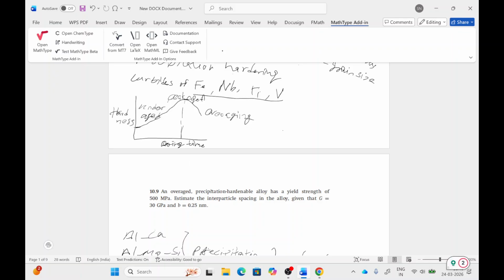In this question, we are asked: an overaged precipitation hardenable alloy has a yield strength of 500 MPa. Estimate the interparticle spacing in the alloy given shear modulus 30 GPa and Burgers vector 0.25 nanometer. We have given yield strength 500 MPa, so the shear strength of this alloy will be half of the yield strength.